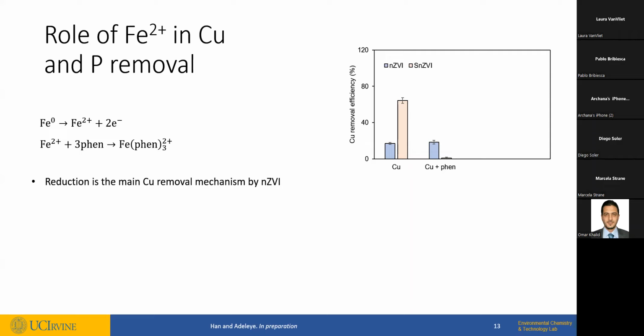All right, but we could also assume that the removal of copper by SNZVI is through Fe2+, but we've done additional studies, and what we concluded from this particular result is phenanthroline can actually also complex with the surface of SNZVI, specifically with the iron sulfide portion of SNZVI. So it's pretty much covering the surface of the particles, and the particle is just ineffective. It's there as if it's not there because its surface is pretty much complexed by phenanthroline.